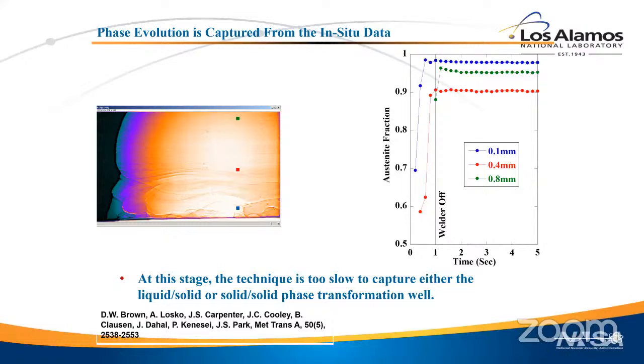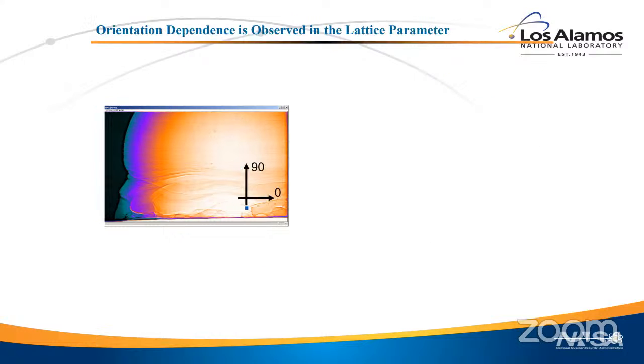Okay, so collecting data every 1 second, you can see the austenite fraction that I'm showing there as a function of time. We really only get 1, maybe 2 data points before the reaction is complete. So the conclusion from here, remember, we're trying to evaluate the technique. That is, in 2017, we weren't ready to take on the ferrite to austenite phase transformation as it quenched because it happened faster than our fastest detector could keep up with it. Okay, so we had to come up with a solution for that because the data wasn't fast enough.